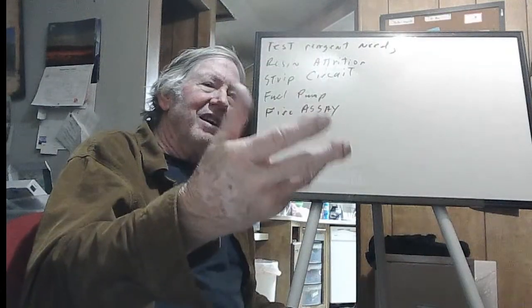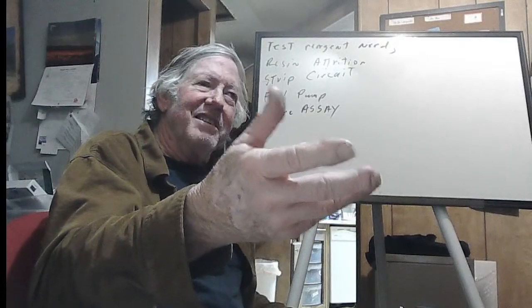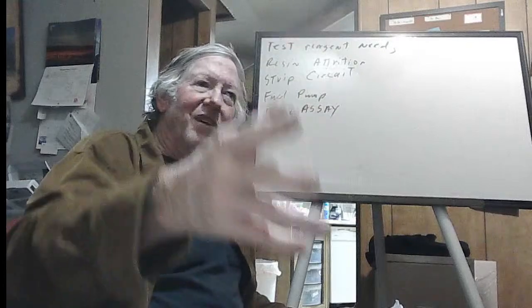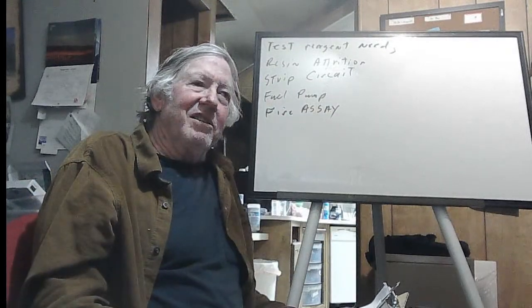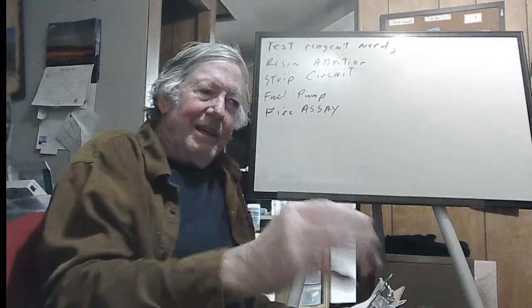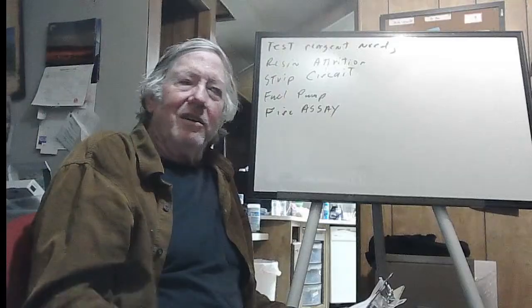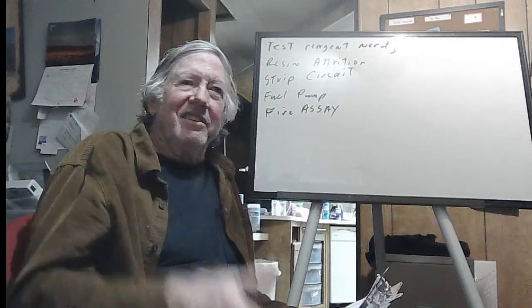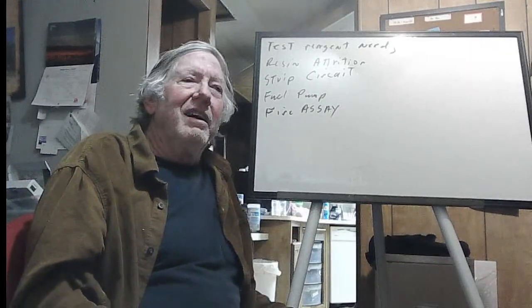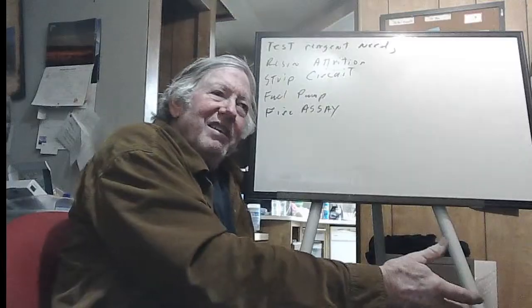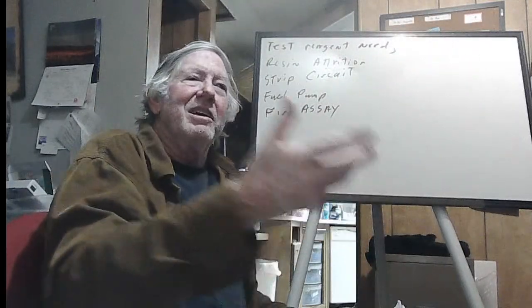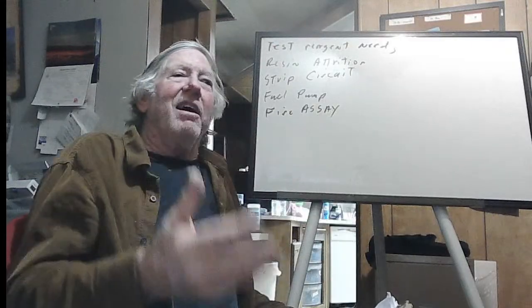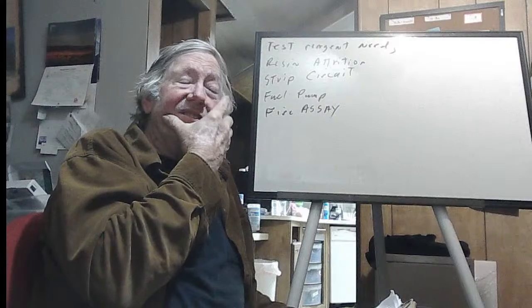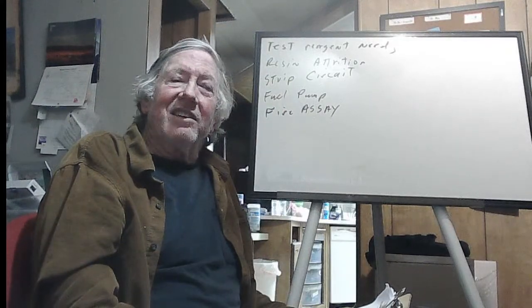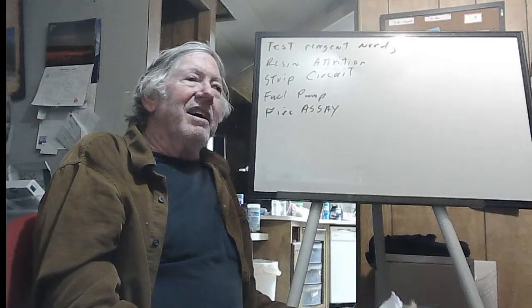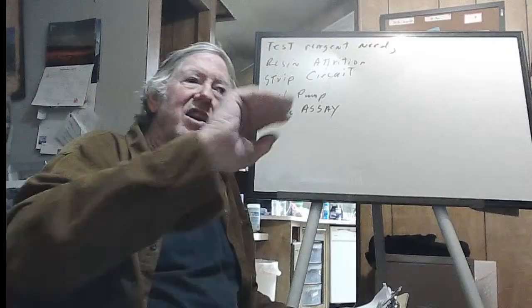At that point, I took one, roasted it for a little bit at 600, and took it out. The other one I roasted for like an hour at 600 degrees, stirring it and putting it back in until it didn't glow anymore. Then I took it back out, call it an additional 10 or 15 minutes of stirring and putting back in. So now I've got one sample taken as slowly and gently as physically possible up to the resin breakdown temperature, where it's starting to actually burn the carbon. The other one, I took up to that temperature and then cooked the heck out of it.